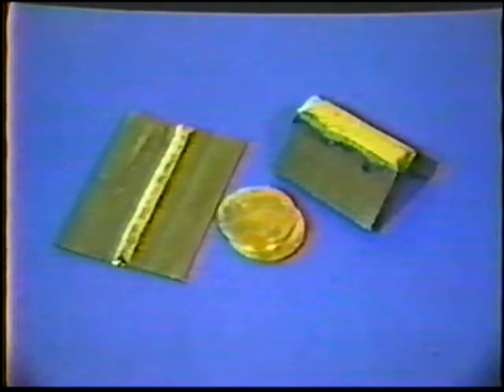Some common braze welding faults are too large a root opening, resulting in excessive reinforcement, not enough heat, which causes a narrow, inconsistent braze weld with lack of penetration in spots, too much oxygen, which causes the weld to be depressed in the root area, too fast a travel speed, which produces a narrow braze weld similar to insufficient heat, and too much heat, which causes the face to be depressed into the root opening. The black edges are the result of burned zinc oxide. However, with care and practice, you should be well able to produce quality braze welds.